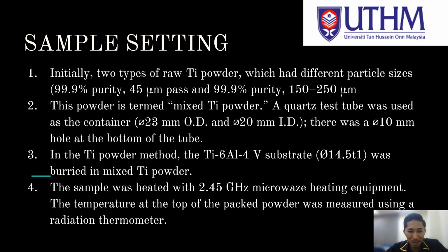In the titanium powder method, the titanium Ti-6Al-4V substrate, 14.5 mm in diameter, was buried in mixed titanium powder. The sample was heated with 2.45 GHz microwave heating equipment. The temperature at the top of the packed powder was measured using a radiation thermometer.